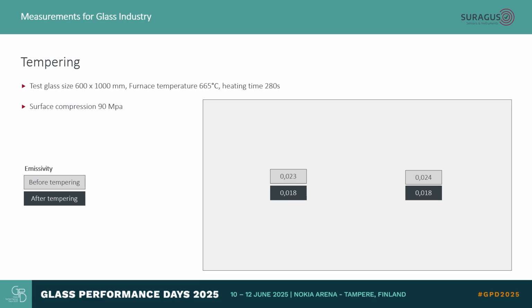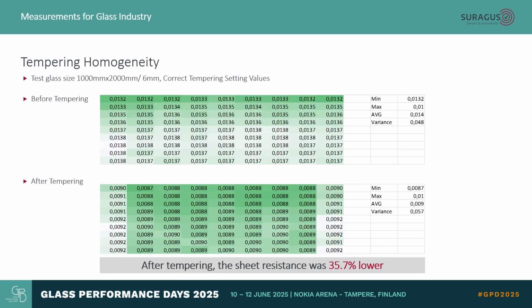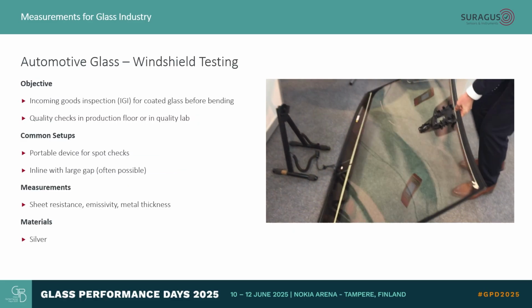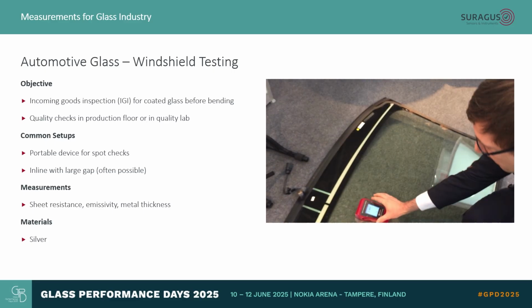The emissivity changes quite a bit, sometimes 30%. Here are some examples from one glass before tempering and after tempering. There's more data. It's a special topic, so I will not go into this too deep, but it's a good application to know the emissivity before the tempering and feed it directly to the furnace.